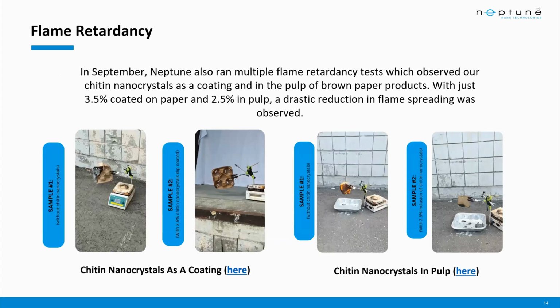But really, beyond just strength, beyond just barrier, beyond bacterial resistance, did you also know that chitin nanocrystal acts as a flame retardant as well? The reason is that it creates char formation on the surface, and the surface chemistry of chitin also allows the release of nitrogen, which is essentially suffocating the fire. This works both as an in-pulp additive and as a surface coating. Here, I'm embedding quite a few of the test videos that we did, but again, it's up and live on our YouTube channel, so please come by and check out these tests in action.